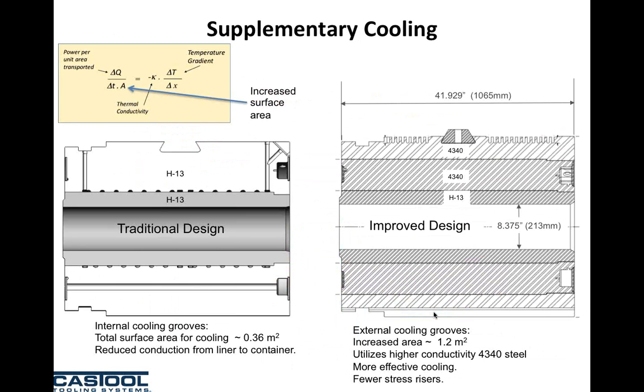Just one sec, Ken. The reason most people air cool the liner when they have heating elements in the center of the mass is that the combination of H11 or H13 or 2343 and 2344, and having the heaters in the center of the mass, doesn't give enough heat dissipation and the liner gets too hot. So the reason people do air cooling between their mantle and the liner is to cool the liner down